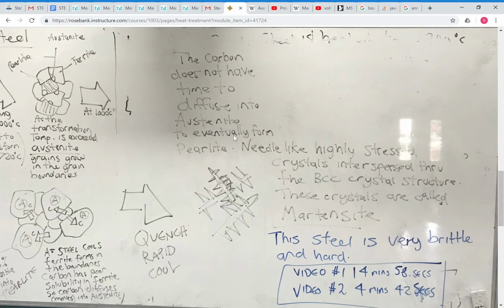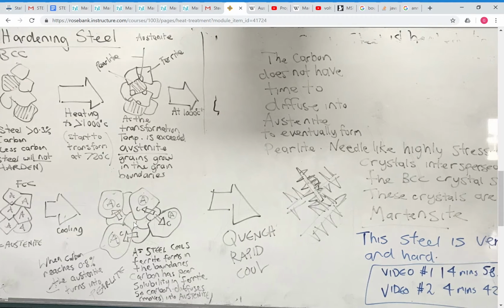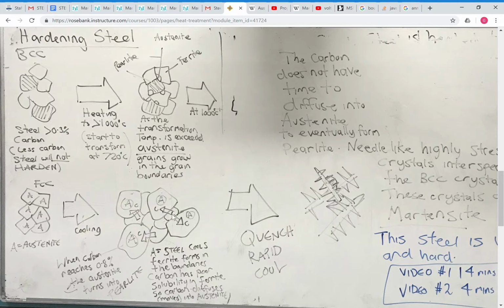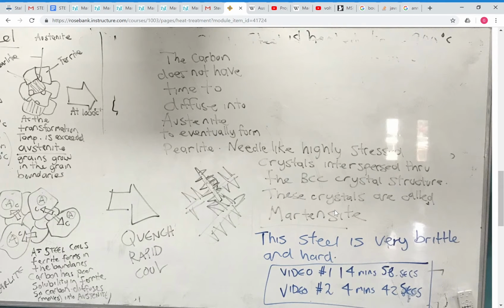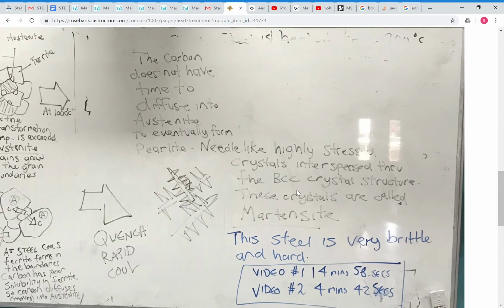So the carbon doesn't have time to diffuse into the austenite when you quench it, when you just drop it from 1,000 degrees straight into the water. So it doesn't have time for this process here where the ferrite forms and the carbon, because it's not soluble in ferrite, jumps into the austenite, and then the austenite becomes pearlite. That diffusion takes time. So there's no time. So what ends up happening is these needle-like, highly stressed crystals that are interspersed through the BCC crystal structure form.